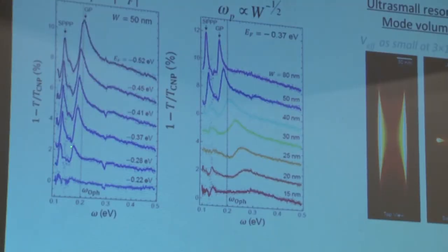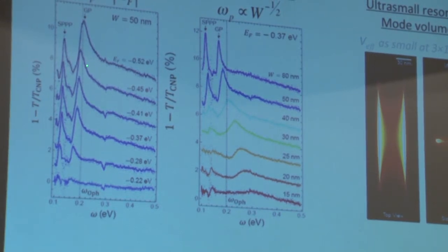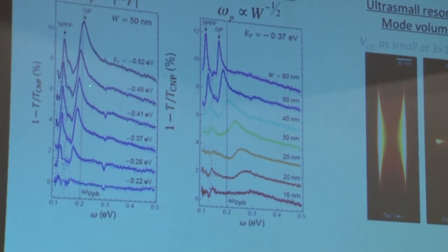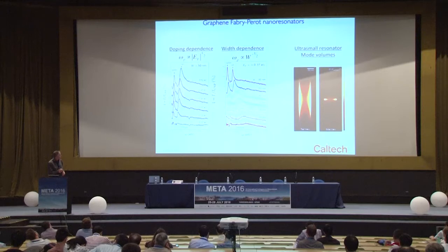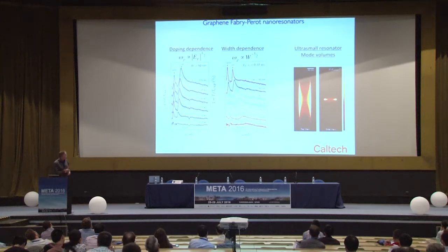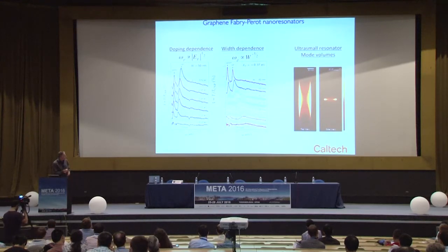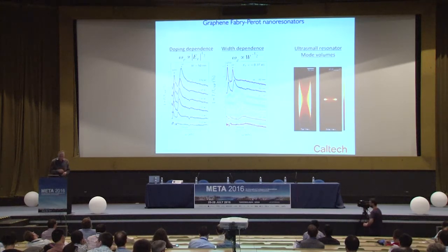They allow us to tune what we see as we change the carrier density from Fermi level positions near the Dirac point to negative potentials that lead to hole doping of graphene. We see the emergence of an electric dipole resonance, a graphene plasmon resonance. And as the carrier density changes, of course, the resonant frequency shifts to higher energies. And we can see also if we change the width of our electric dipole resonator, we can induce at a constant carrier density a change in resonant frequency here over quite a wide range, even above this energy, which is the optical phonon energy in graphene.